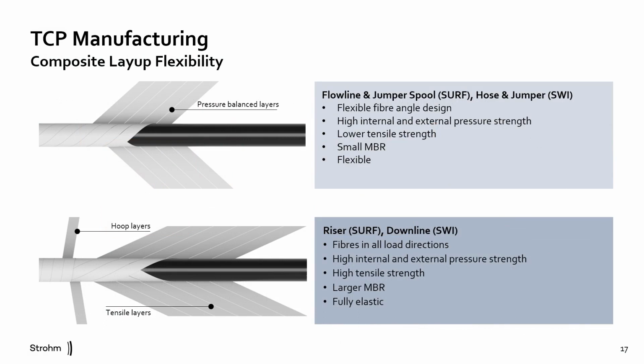As mentioned earlier, the key advantage of a composite structure is that by placing the fibers in the right direction at the right location, we have an incredibly fine level of control and can tailor its performance to any application. What this actually means is that for any tape layer throughout the composite laminate section, we dictate the specific angle at which we lay the tape.